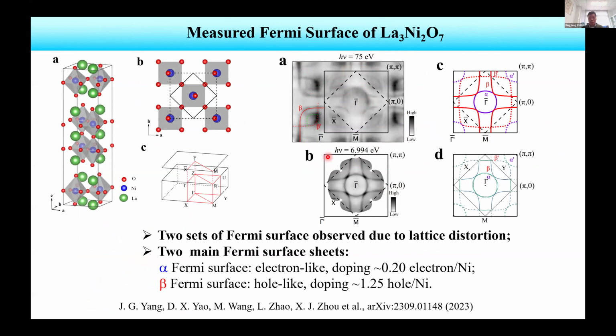Also, in our lab, we use laser to gather the Fermi surface. This is the Fermi surface obtained from laser. Basically, because in the lanthanum 327 system there's some lattice distortion, that means there's some octahedral rotation. That's why there's something like a root 2 by root 2 structural distortion, and that's why we can observe two sets of Fermi surface.